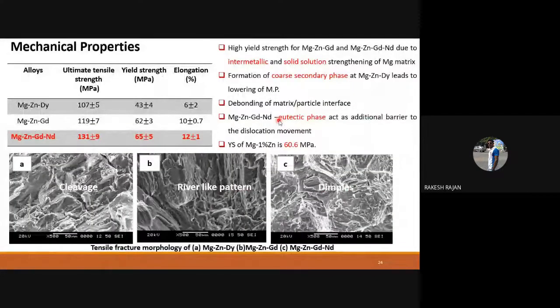So for mechanical properties, an electronic tensometer has been used to understand the mechanical property of this material. We have seen that there are three alloys we have developed for the studies, and out of those, the quaternary system, magnesium zinc gadolinium neodymium, gives better mechanical properties. This is mainly because, as I have told you, of the better intermetallic formation, long period stacking phase formation, and the uniform microstructure.